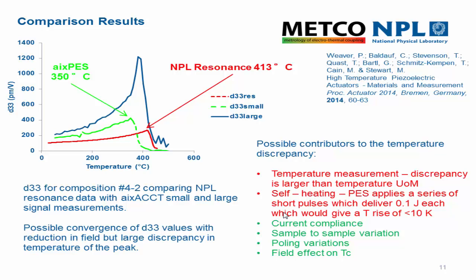One factor which could be involved is self-heating, because the materials become conductive at higher temperature. When we apply a high electric field, the sample self-heats, and so really this sample, when it says it's 400, may actually be 400 plus whatever the self-heating effect is. But the aixPES system applies a series of pulses. They're not very long pulses, and we can't see that would explain all of that temperature difference.